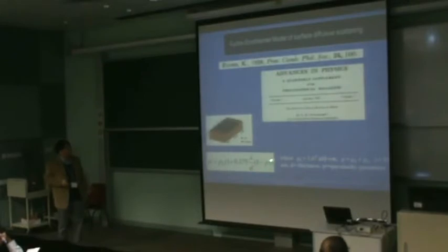So this work was done by Fuchs, and so essentially, our idea is very simple. If you have disorder scattering, you have surface roughness, you're going to scatter your momentum, and which is bad for conduction. So maybe we can put some atoms on top and smooth out this surface roughness. Maybe you will have less scattering, and then you can improve your p. So if you look at this formula, when p equals 1, this term disappears. You just have bulk resistivity. But if p is equal to 0, then this term is very big, and then you have the surface roughness.